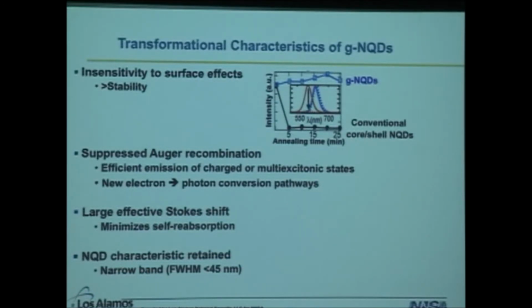Of course, we view the giant dots as somewhat transformational in this area. We've demonstrated that their emission properties are generally insensitive to surface effects, so we can put these in the solid state. We can replace their ligands with something that's volatile, pump on them and heat them up, and we find that the emission from the giant dot stays the same. Compare that to a conventional core-shell quantum dot, where after 5 minutes of annealing the emission from the conventional system is gone.